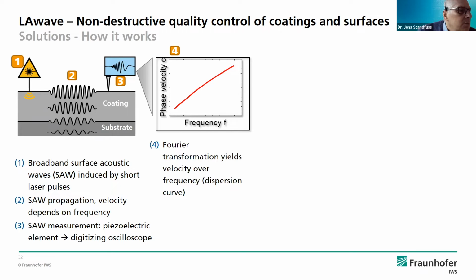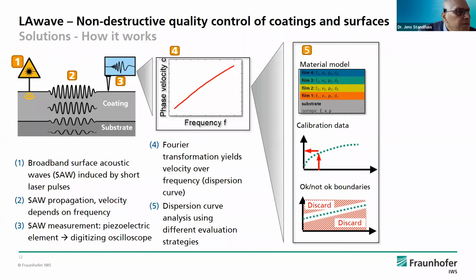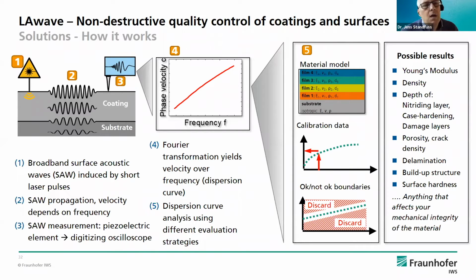And then you see from the values, especially from the propagation values, from the phase velocity over the frequency, some so-called dispersion curves. And based on these dispersion curves, you get different values with respect to the coating technology. And at the end of the day, you can measure and determine, non-destructively, the Young's modulus, for instance, of the layer. So you get some information of the density, the depth of the layer, and also of the hardening, for instance, and also if there are some damages inside: porosity, cracks, delaminations.